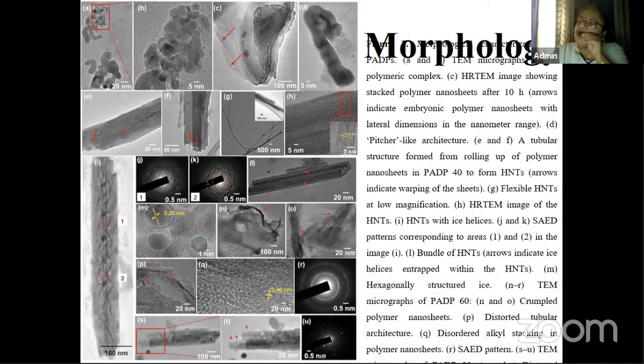We envisaged that water inside the hydrophobic channels would freeze spontaneously, clustering into the nano-confined environment and providing a signature for the emergence of quasi 1D ice helix. Why am I saying quasi 1D? Because first it was the sheet, and then they buckle out, and then it forms the tubes. So inside you cannot call it perfectly one dimensional, because the structured water was two dimensional, and when the sheets were rolled up, they gave the signature for the emergence of quasi one dimensional ice helix.